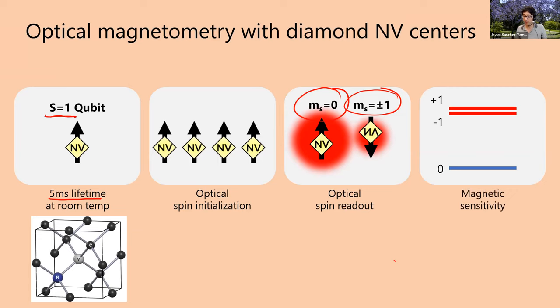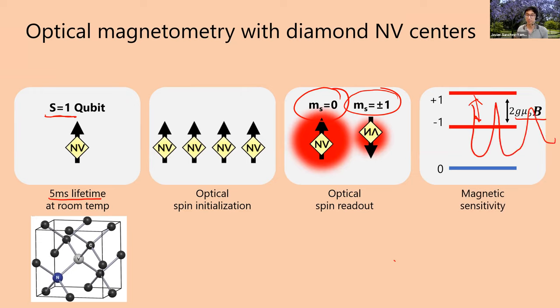And the last important quality is that because it is a spin one system, it has a magnetic dipole moment. It is sensitive to magnetic fields via the Zeeman effect, which will split these plus-minus one levels. So you have this level structure, which is sensitive to magnetic fields, and you can address it by shining in AC magnetic fields at microwave frequencies, address these transitions, do spectroscopy, and in the end measure the magnetic field. And that's how you can do magnetometry.